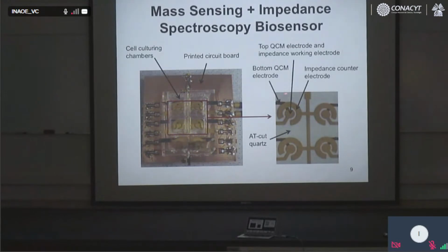So here is the top surface, and this is the combination of the two sensors. Here we have one, two, three, four sensors. The substrate is quartz crystal, and then what you can see here is the top electrode of the quartz crystal microbalance, which is also the working electrode for impedance spectroscopy. Impedance spectroscopy requires two electrodes. This is the second electrode, which is called a counter electrode.